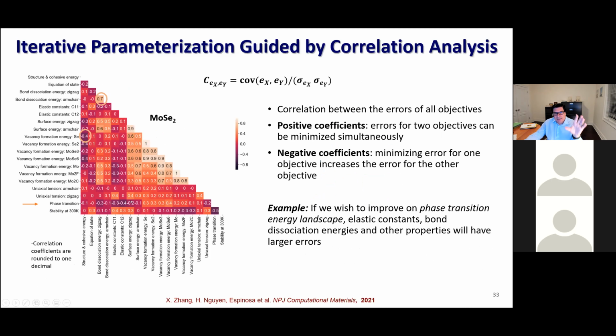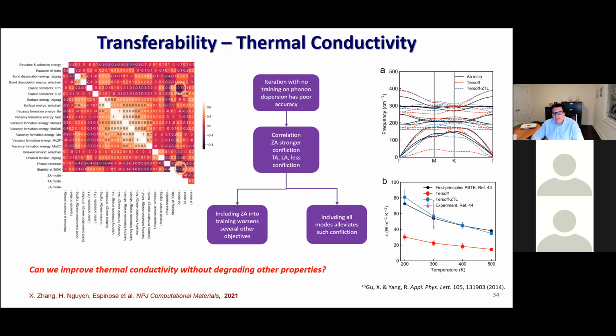And I explained this idea that you have a competition between variables. So it's not something where you can say, okay, if I include more properties, I will automatically be able to recover them with computational accuracy. And I will show you how we use these metrics in the case of phonon dispersion. So the black is the DFT data, the first three acoustic modes, and then optical modes. These are frequency versus wave number. And the prediction of the Tersoff that I just showed you for one mode, one acoustic mode that is the out-of-plane bending mode, is very far from the DFT data.